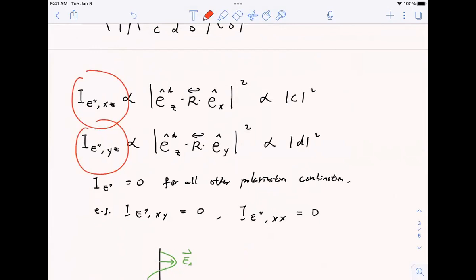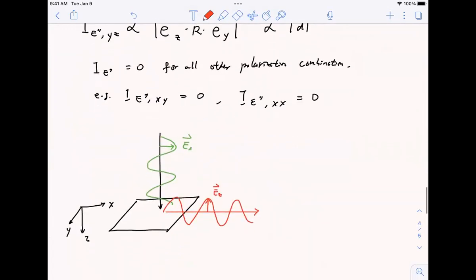The same, you shine the X or Y, either way is fine. You get a Raman propagating with a Z polarization, because the wave vector of light is perpendicular to the polarization. So you know that the scattered light will be in plane. So that's why in our geometry, if you put the objective here, shine the light and collect the same light, you are not going to get anything.